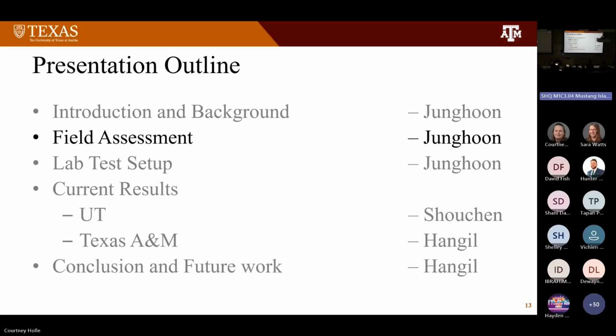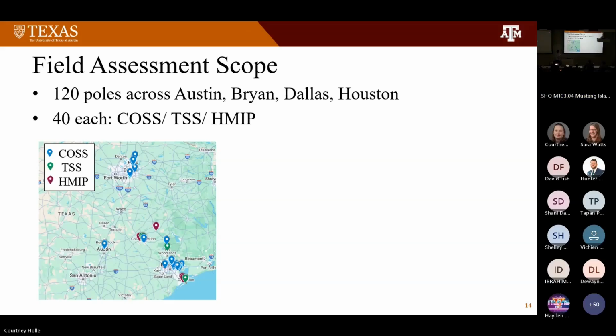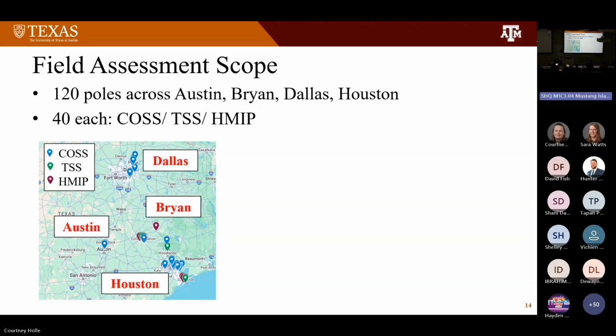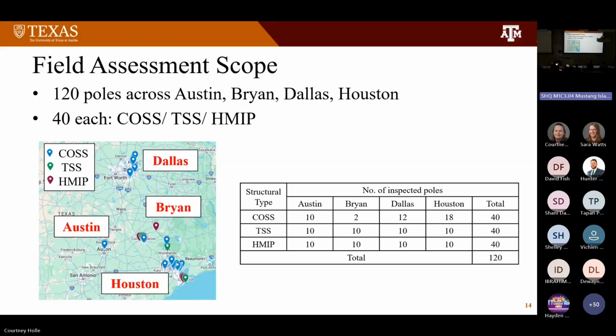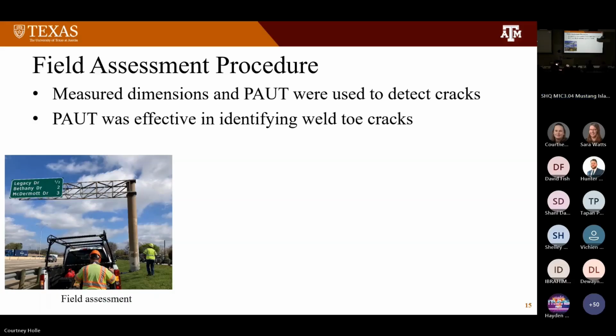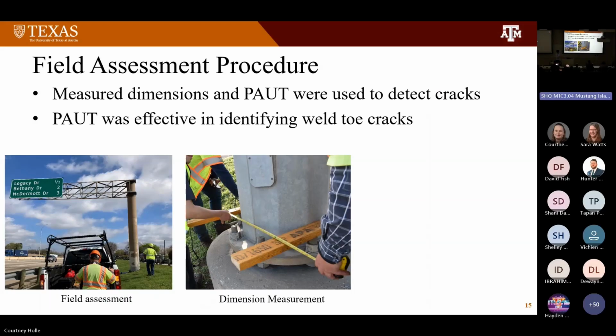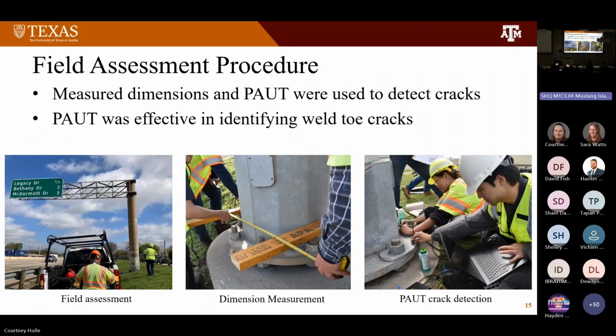So let's move on to the field assessment. We inspected poles in 4 different regions across Texas: Austin, Bryan, Dallas, and Houston. And a total of 120 poles were inspected, 40 for each type of structure. Field assessment involves measuring the structure dimensions first, and then using PAUT to identify the crack locations.